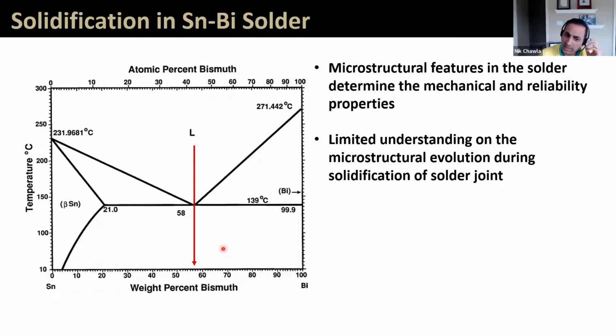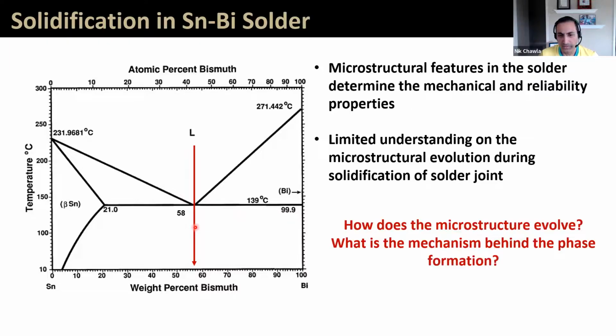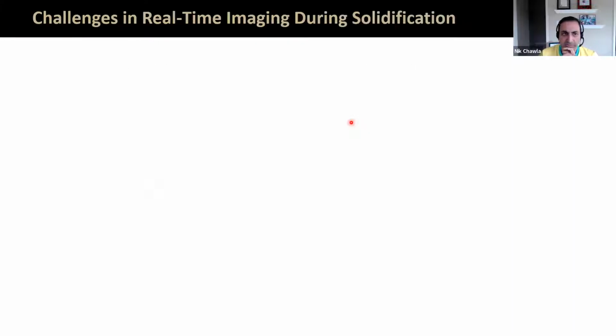So tin bismuth has this kind of phase diagram. It's a binary. The eutectic occurs around 58% bismuth or so, and it has a melting point of around 139 degrees C. And there's very limited understanding of how the microstructure evolves when we go from the liquid state to the eutectic microstructure. So some of the questions we wanted to answer were, how does the microstructure evolve, and what are the mechanisms behind this phase formation?